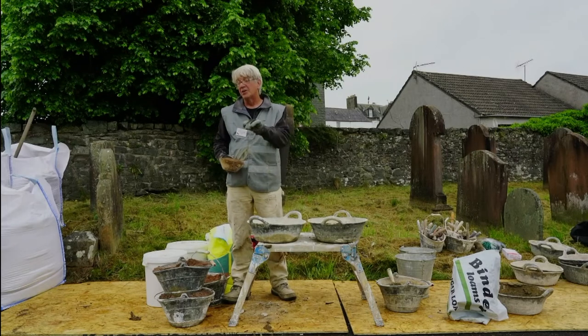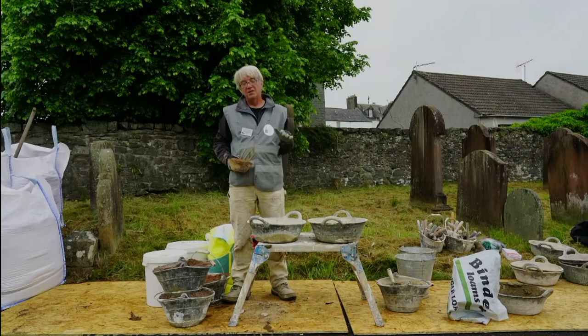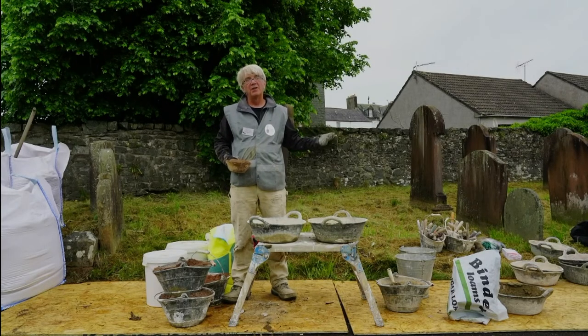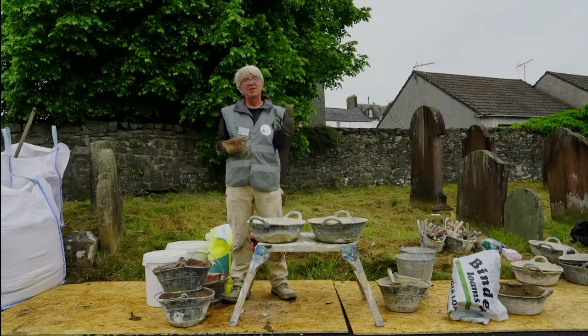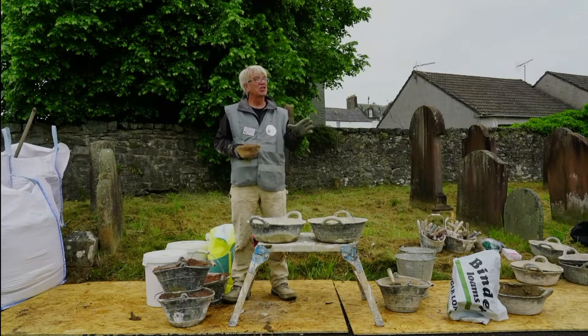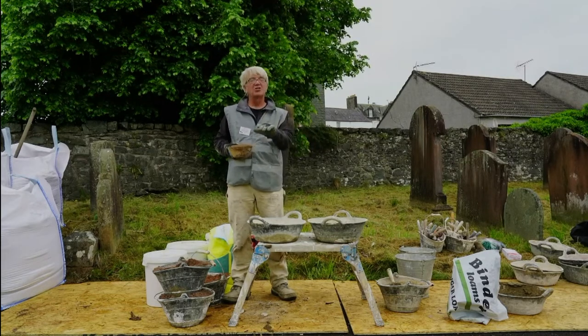The reason we would say that you don't use fine sharp sand, and I'd stress that, fine sharp, it still has to be sharp, is that it would shrink far too much. My experience is the opposite of that. It shrinks less than if I made it all with a coarse sharp sand. So this is still evolving thinking in my head, but we can't keep ignoring the fact that most of the mortars we see historically are made with really fine aggregate. And it's not just because they couldn't get sharp aggregate. So that's just food for thought, yeah?